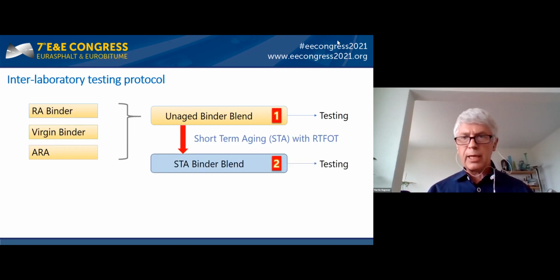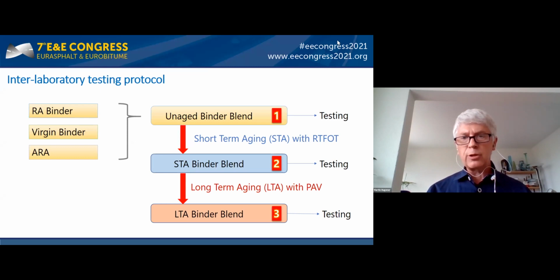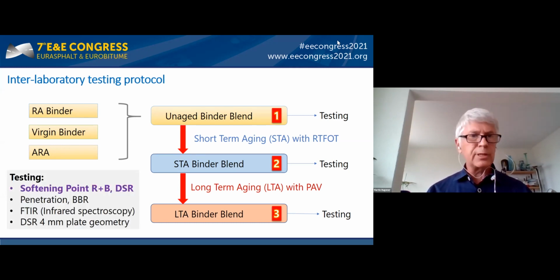You make the short-term aging using a rolling thin film oven test. Then you test again and make the long-term aging using the pressure aging vessel. Then you test this blend again. Actually, this looks quite straightforward, but still we had a few problems to solve. For example, the reclaimed asphalt binder, you cannot buy it from a company. You have to make it by yourself. This means that you have to extract the reclaimed asphalt and recover the binder. So we had to choose between sending out the reclaimed asphalt to every lab, and then every lab can do the extraction and the recovery by themselves.